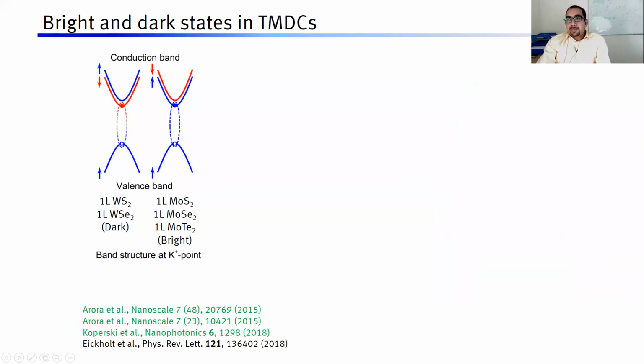Now, there are 2 types of these transition metal dichalcogenides, or these monolayers. One are tungsten based and one are molybdenum based. You can have tungsten disulfide, diselenide, MoS2, MoSe2, MoTe2. And theoretically, it was suggested around 2014 that the tungsten disulfide and tungsten diselenide should be optically dark materials. What this means is that the conduction band has a splitting, and the bottom of the conduction band has electrons only available with downspin, and the second conduction band, the higher energy one, should only have electrons with upspin. Okay, the spins can be inverted, but let's not go into details.